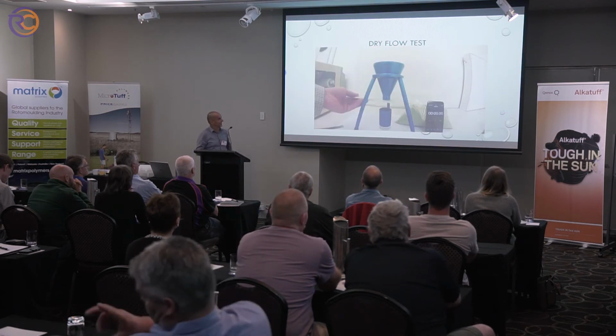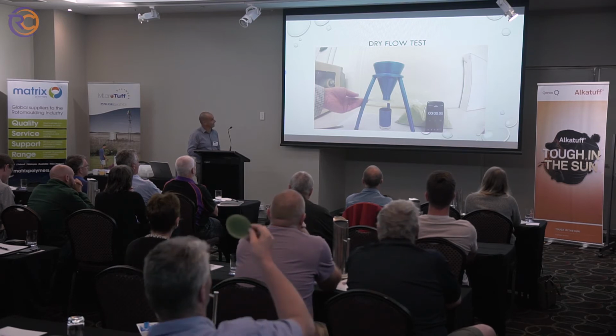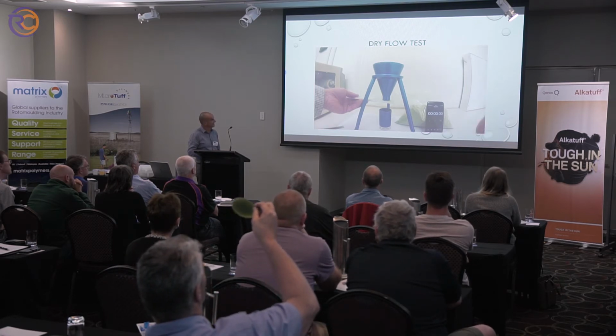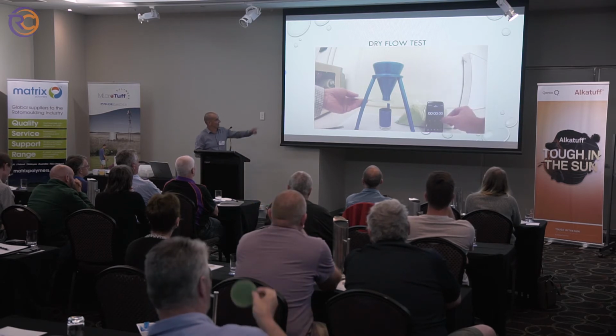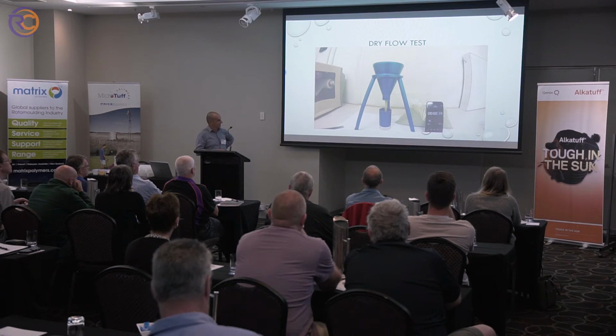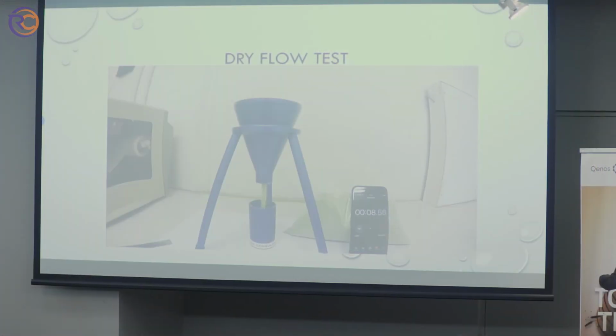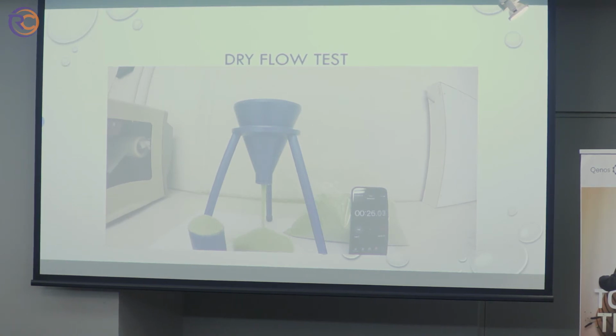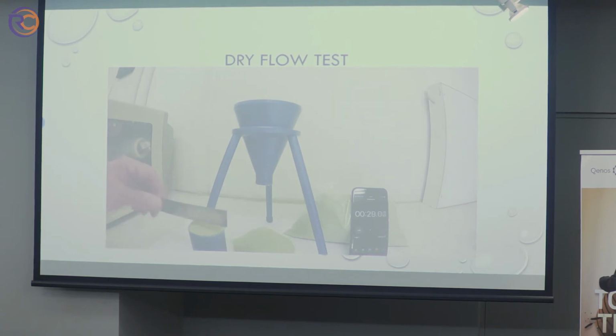So this is an actual test of the dry flow test being conducted. And we're just holding the powder in the funnel, let it go. In this case, just using a phone to measure the amount of seconds it takes for the powder to flow through. We actually put 100 grams of powder in the funnel. And this is another test, which I'll talk about in a minute. The powder goes into the cup, and that cup measures the bulk density. And that's measuring how well the powder will pack down. So the dry flow for that particular powder was about 27 seconds.